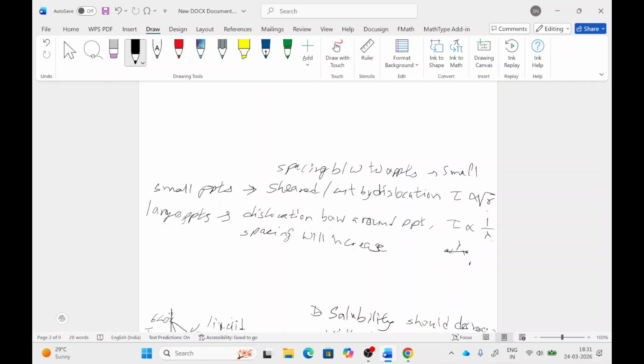So the bowing around the precipitate we can consider as these two precipitates with a dislocation line. The dislocation is moving towards the precipitate, and at the second stage it bows around like this. The dislocation line tries to move through the precipitates, so it bows, and that results further. This is the lambda distance.